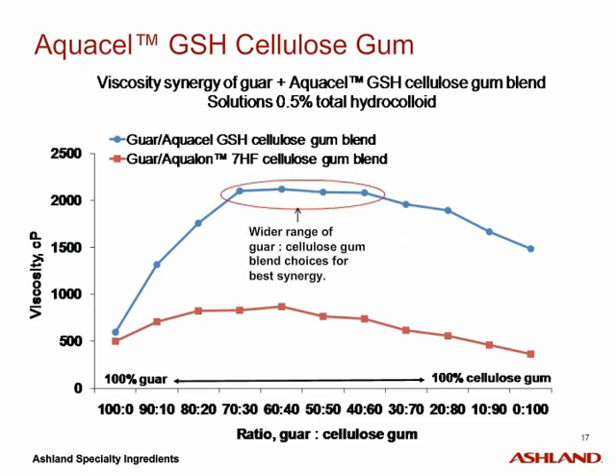Another key finding from the testing is that the viscosity of blends of guar and Aquacel GSH cellulose gum were similar across a wider range of ratios than previously reported. This chart is showing how guar and Aquacel GSH cellulose gum blend ratios of 70-30 to 40-60 all exhibit high viscosity. This gives a wide working range of blend ratios where the synergistic viscosity can be leveraged in formulations.